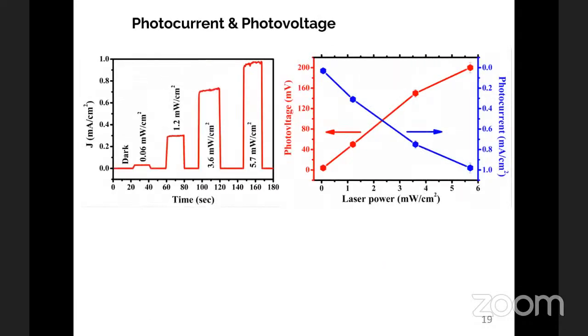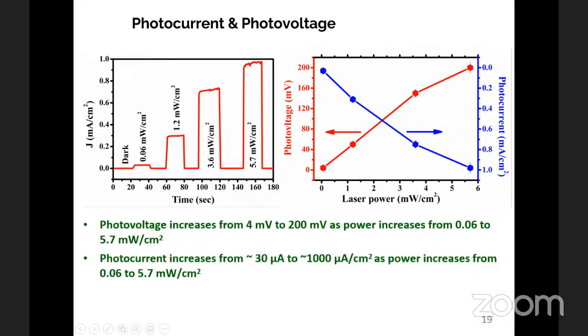I also calculated the photocurrent and photovoltage for different laser powers. Compared to dark, you can clearly see the increase in the photocurrent with respect to the different powers, and the maximum photovoltage is calculated to be around 200 millivolts at a laser power of 5.7 milliwatt per centimeter squared. Of course, these photocurrents can be increased if you go beyond this power. The photocurrent also shows an increasing tendency with increased laser power, because when you shine more photons, it gives you more photocurrent.